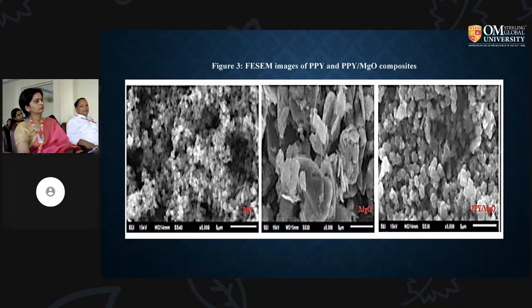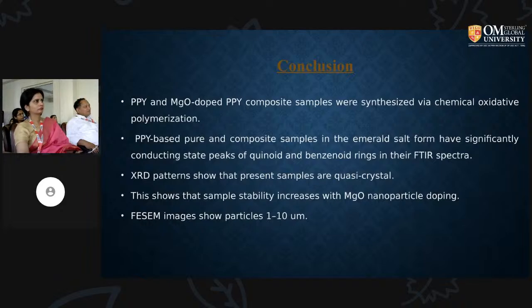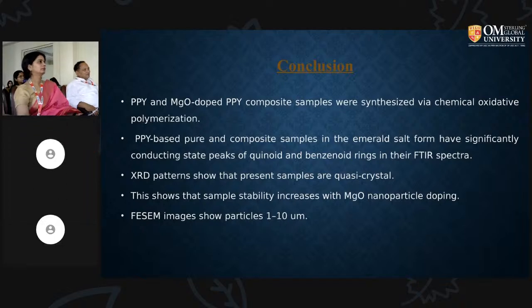Conclusion. Polypyrrole and magnesium oxide doped polypyrrole composite samples were synthesized via chemical oxidative polymerization. Polypyrrole based pure and composite samples in emeraldine salt form have significant conducting peaks of the quinoid and benzenoid rings in the FTIR spectrum, and the XRD pattern shows the present samples are quasi-crystalline. This shows that the sample stability increases with magnesium oxide nanoparticle doping. FESEM shows particles of 1 to 10 micrometers.